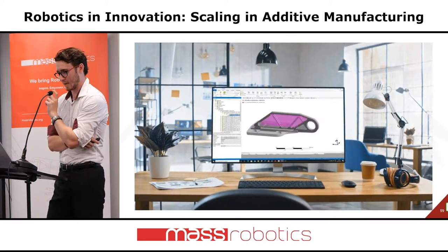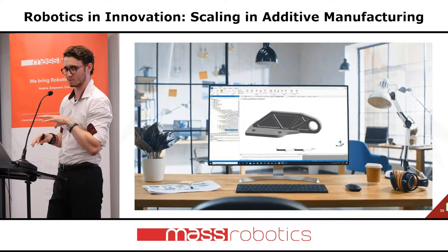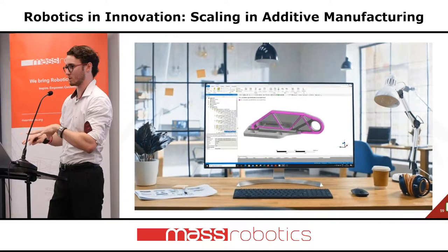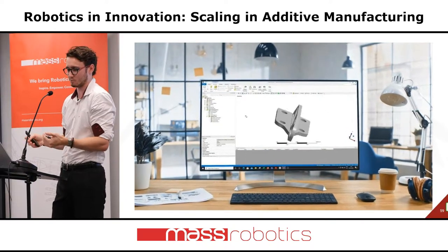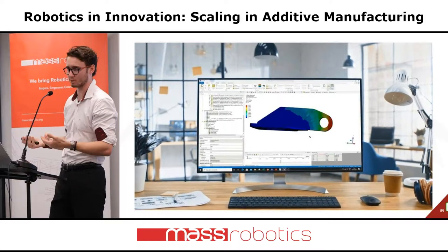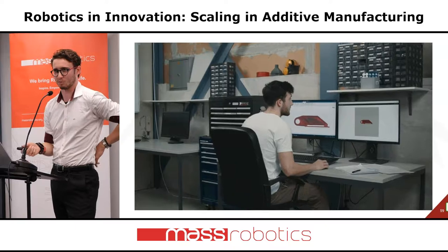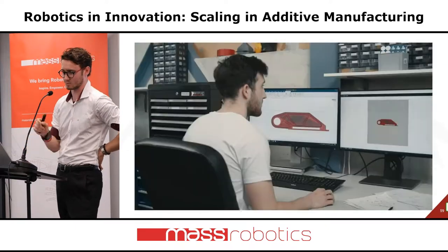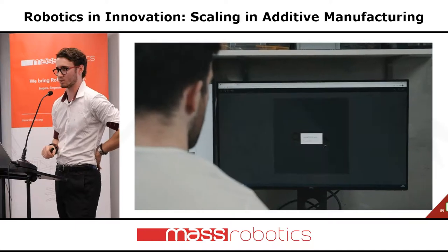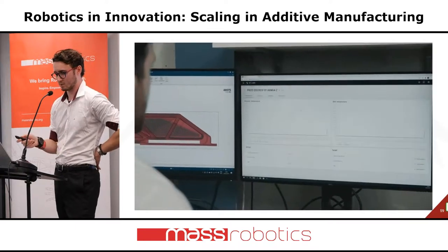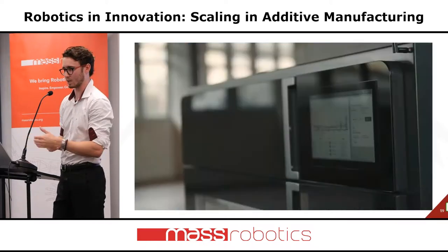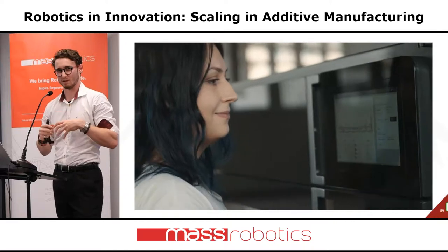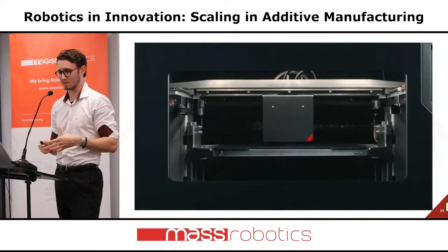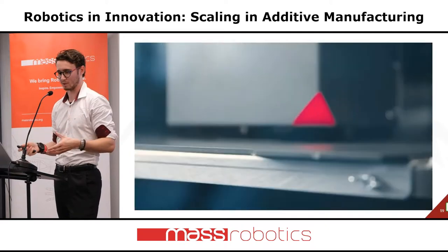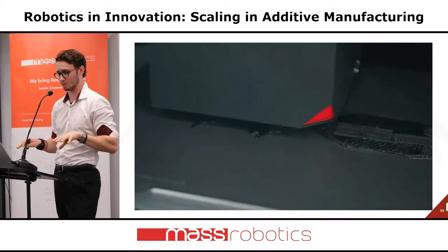So you'll see kind of how strong this part is, and showing off this more or less batch printing where you can print these flat preforms and they're all 2D, but then you can reassemble the part and have like a 3D fiber architecture. There's no other process where you can lay in tape into these fine details, especially like a rib section. So we also have this production suite where you can have a local network at your site at an OEM or supplier where you can have everything. Again, IP was mentioned. So same idea, if you want to keep all your IP in-house, you can do that with our technology, and all your build modules are connected and all of your fusion modules are connected, so you can see all the data and have all the analytics.